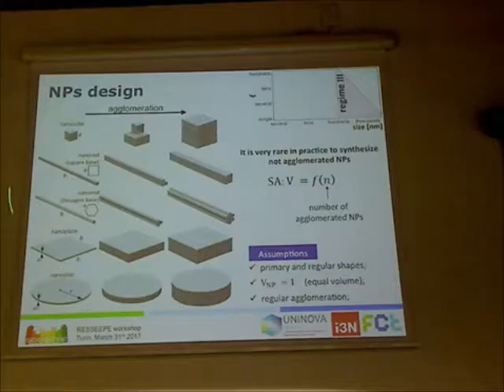It's very typical to happen this when you try to create your own particles at lab scale. They start to aggregate to form these kind of shapes. And you see, for instance, 2D plates start to aggregate, you become close to a cube.